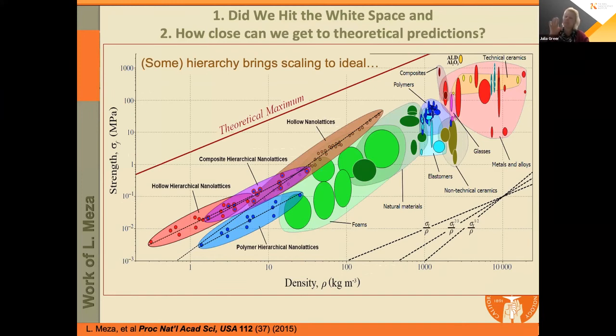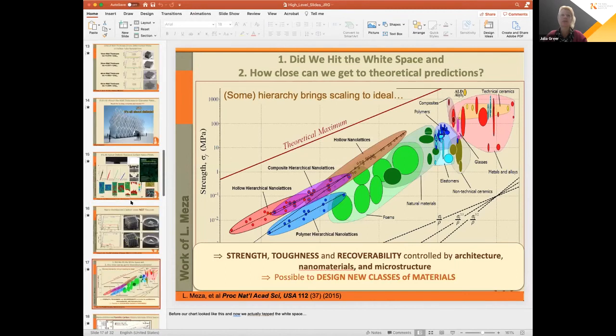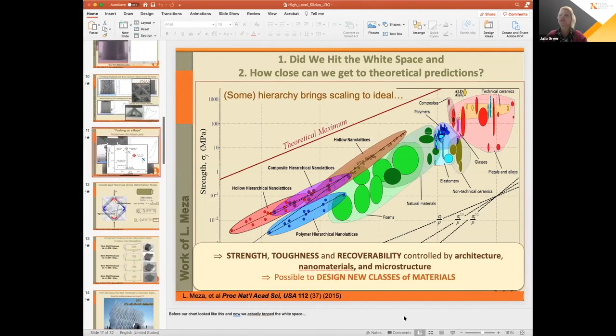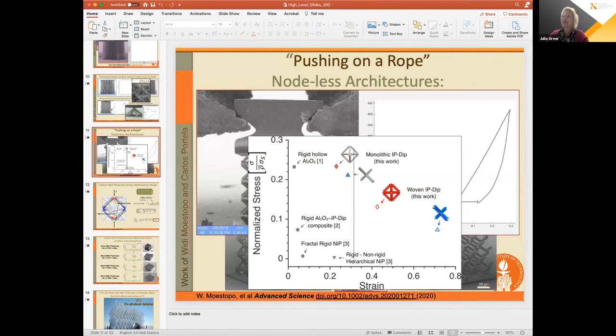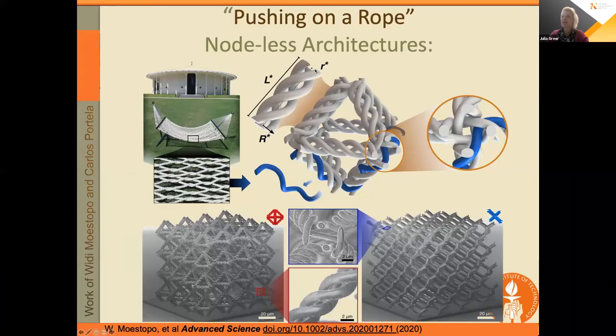So as a collective response, they don't fail the material. The structure is effectively resilient against defects in the sense that the overall response is not affected too much. But at the local scale, of course, there's damage initiation. And that's one of the reasons why we turn to these node-free architectures where we don't see this kind of level of damage accumulation. So just to show you one more time, you can see that these interwoven architectures don't have a single node. And so there are no stress concentrations. And in that sense, just like you were bringing up, it's bending and twisting that's accommodating the strain. And then there's no damage accumulation.